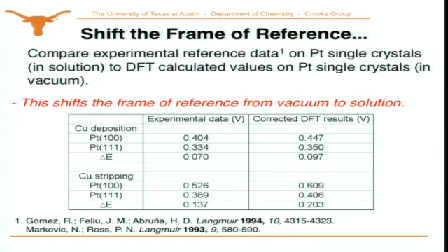And finally, we made one more adjustment. And this was a very good idea by our theorist friends. What they did was they went into the literature of bulk copper UPD, and they did a DFT calculation for bulk deposition of copper, and then compared that to the experimental number. They were close, but not exactly the same. And so they generated a correction factor from the DFT number to the experimental number, just a few tens of millivolts, and said, okay, let's apply that same correction to these nanoparticles. Because our DFT is off a little bit, let's correct the nanoparticle number for the amount that we know it's off on the bulk.